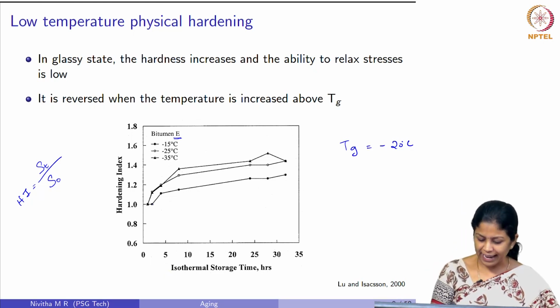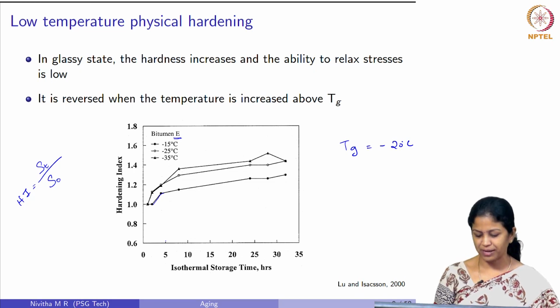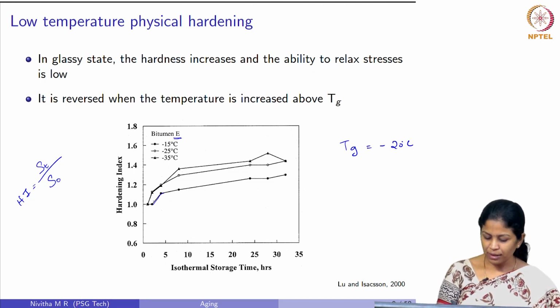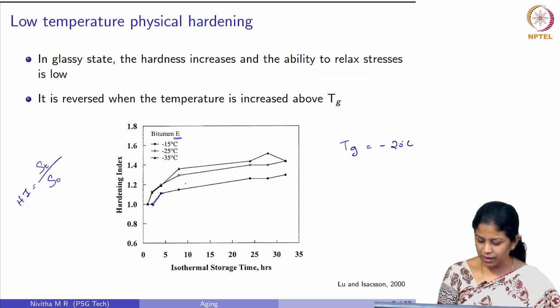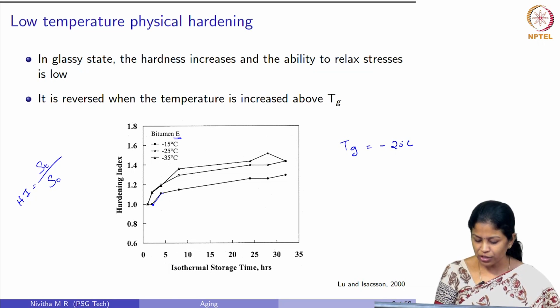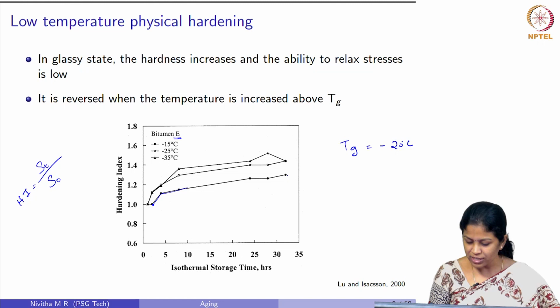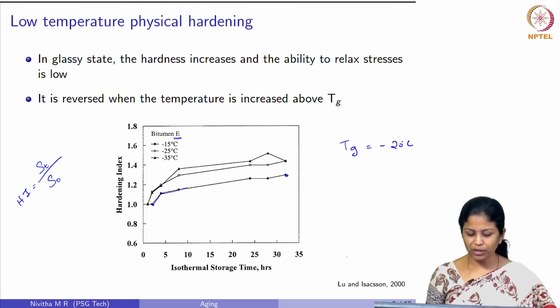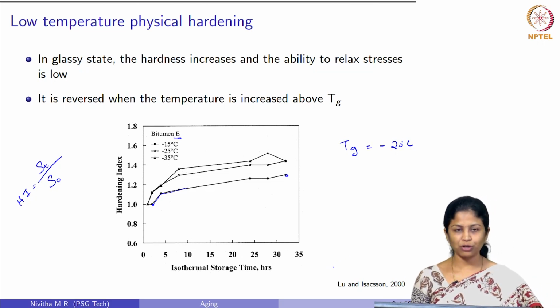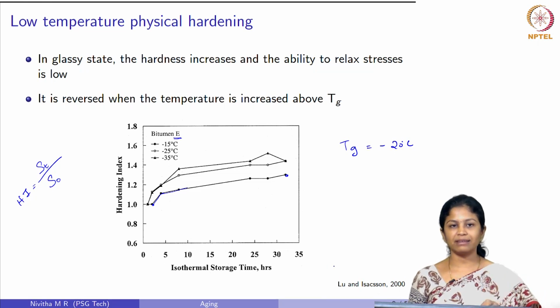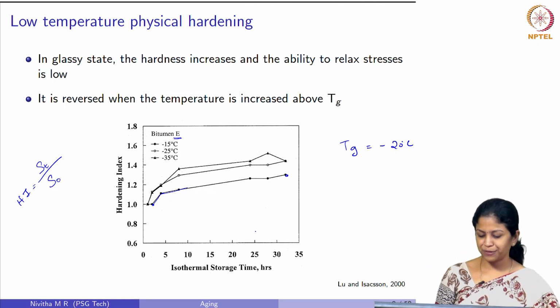So, this line here corresponds to -15 degrees Celsius. Initially they have measured it, this is the starting point, and then when it is measured after close to 5 hours of storage, they see about 1.1 times increase in stiffness, and with time you can see after 30 hours of storage it has reached more than 1.2 times increase in stiffness compared to when the temperature was immediately reduced to -15 degrees Celsius, right. So, this is for -15 degrees Celsius.